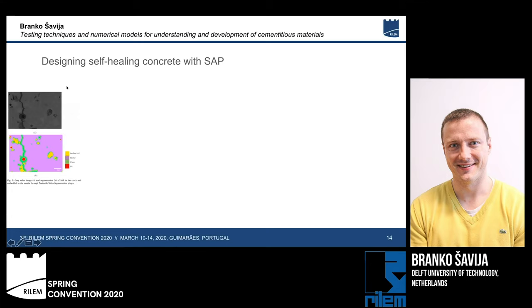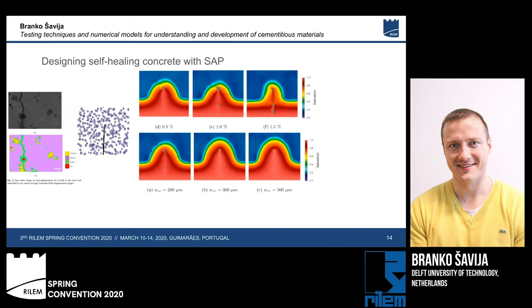We can also do the same thing in our model, where we can pack our SAP particles in a volume. We can crack that volume, and then we can study what happens in this crack. So we can simulate the kinetics of the swelling of our particle and see how that affects capillary absorption of water in cementitious materials. This is much easier done with a model than it is with experiments.